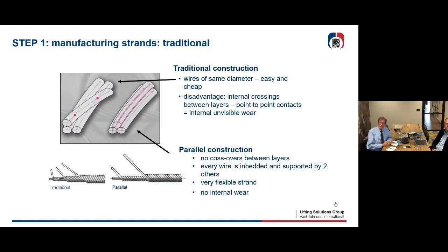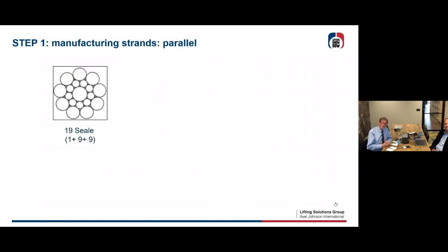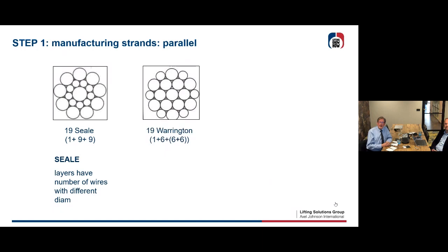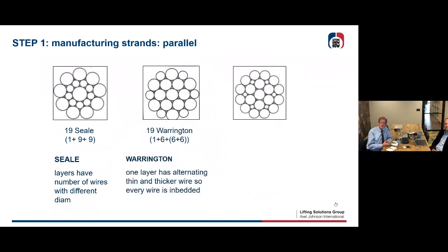And that's why they invented the parallel construction. The parallel construction is that kind of construction where every wire is embedded in two layer wires. If you bend that, you don't have point-to-point contacts, and this will give you a very flexible strand. There will be no internal wear, no crossover. So every wire is embedded and supported by two underneath. To obtain this, we need another construction, and I show you here some of these parallel constructions.